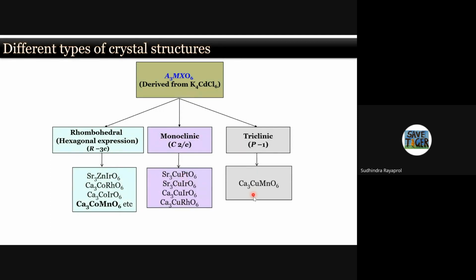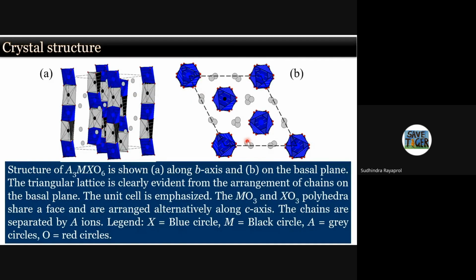But there's one exception to that. If you have calcium, copper, manganese, it is still lower than monoclinic. It has the lowest symmetry. It's mainly again a copper-based system which has this kind of properties. So you have composition, you have structures, and you have a variety of magnetic properties which are available within these stoichiometric compositions. Now, here again you can see the structure is drawn like this.